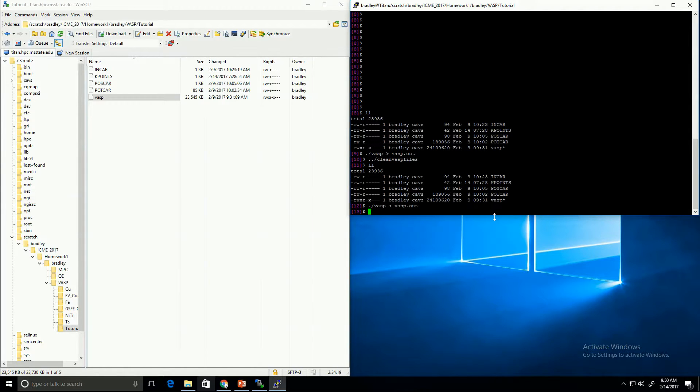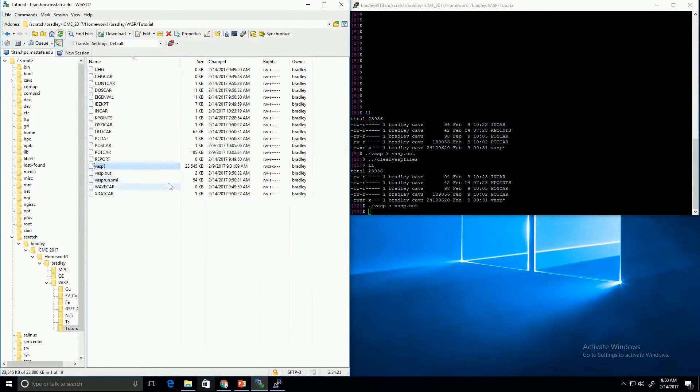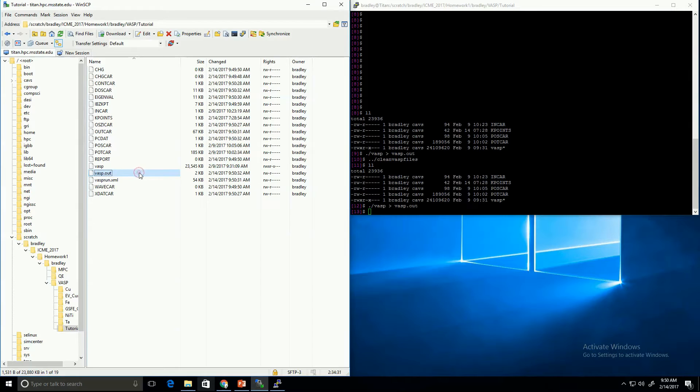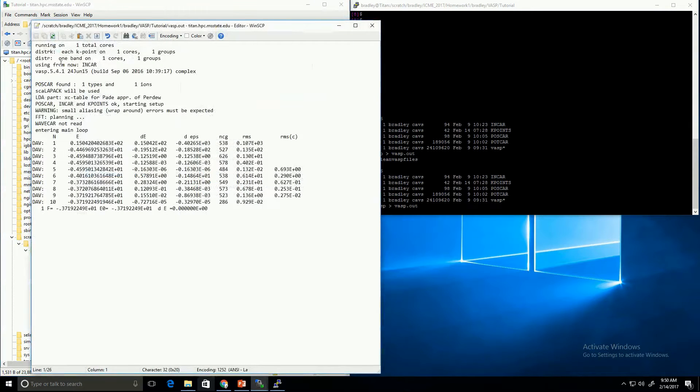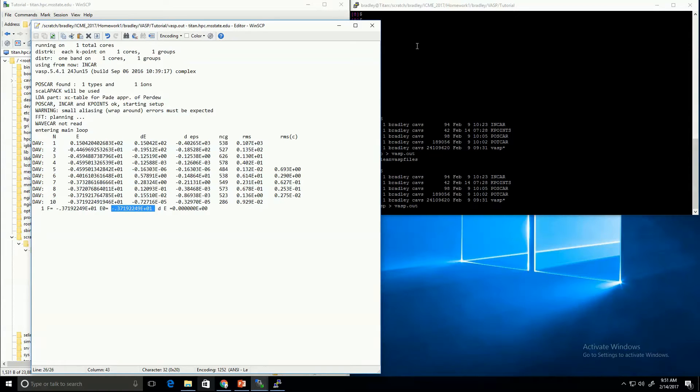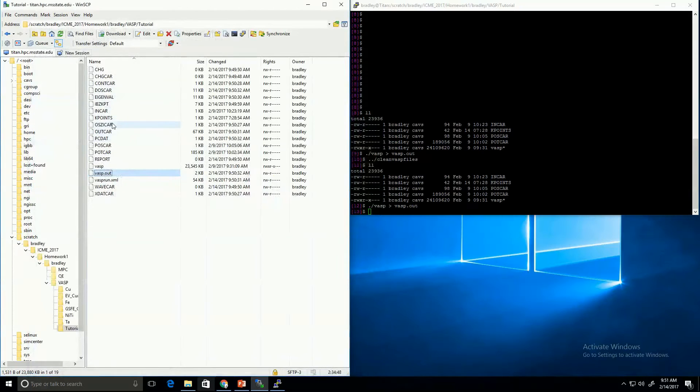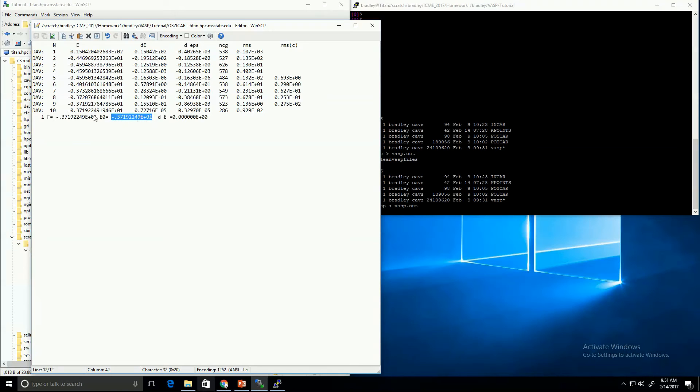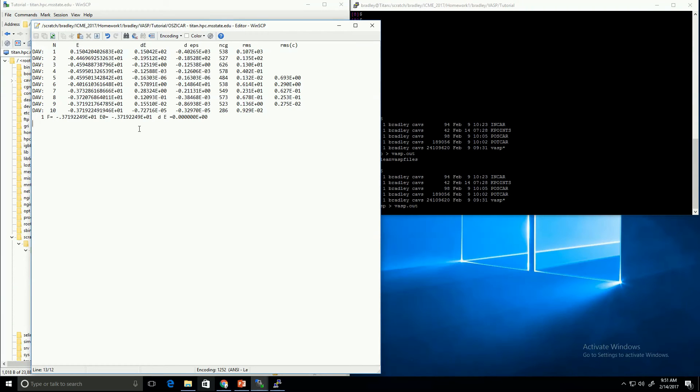And there, now we see it's done. So if we refresh this, we can see all the output files that I mentioned before from the workflow diagram. If we look at this, we can see the standard out that VASP created. We can see it gives information about the kind of run. And then it goes through these iterations where it's converging on the final energy. But all this is coming from the standard out. You can also find this information in an actual output file, which is the OUTCAR file. And here again, you can see the iterations and the converged answer. So, this is actually your answer that you're looking for here. The ground state energy of copper, negative 3.719 electron volts. And there you have it.